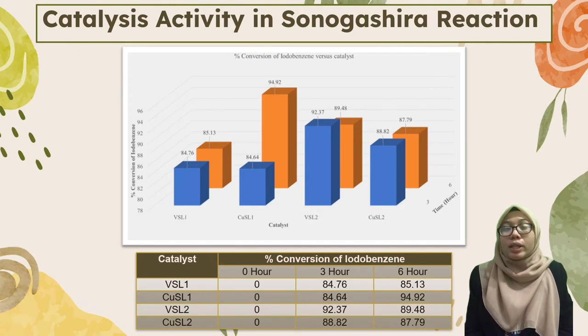For catalysis application, CuSL1 exhibited the highest percent conversion of iodobenzene of 94.92% at 6 hours of reaction, followed by VSL2 with 89.48% at 6 hours of reaction. This value is in concordance with the reported value in research done by Sutrada in 2020. SL1 was identified as the best ligand since the catalytic activities for its metal complexes were higher than SL2 metal complexes. This is because SL1 metal complexes showed positive increment of percent conversion of iodobenzene from 3 hours to 6 hours as opposed to SL2 metal complexes.